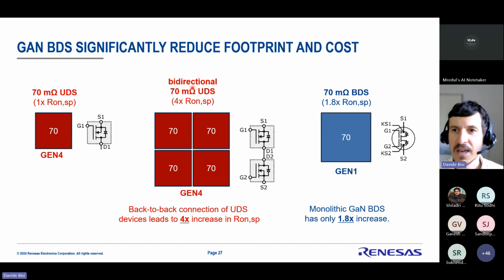So you see that back-to-back connection gives you a 4 times increase in chip area if you do it with discrete devices. If you do it with the monolithic integration, you can see actually that we can do a 70 milliohm bidirectional GaN with only a 1.8x increase in specific Ron. So it is a significant improvement from discrete to a monolithic integration. You can see here the symbol of the monolithic GaN bidirectional switch with the 2 sources, the 2 gates, and here you can also see the 2 Kelvin sources that will come in the next generation of products.